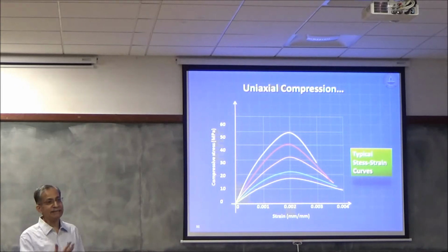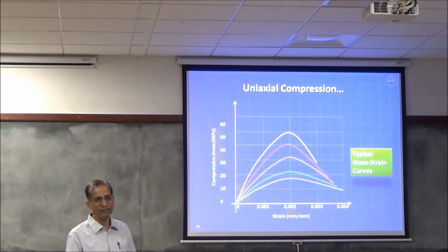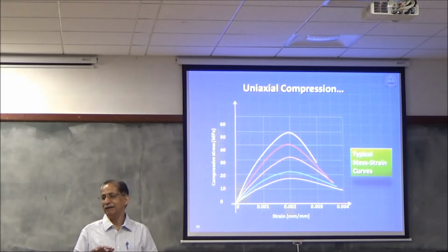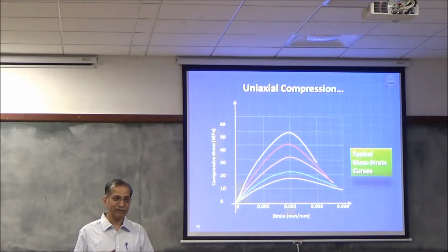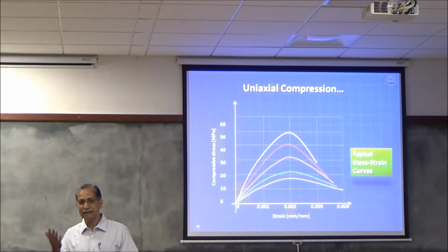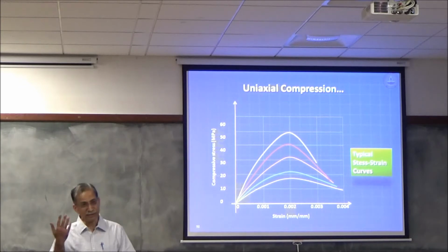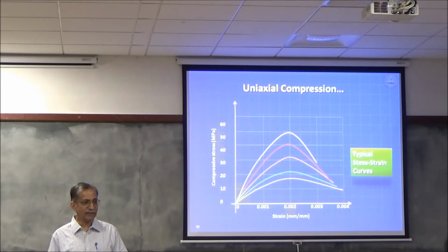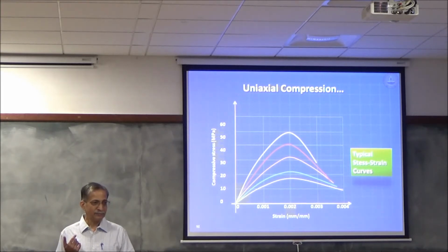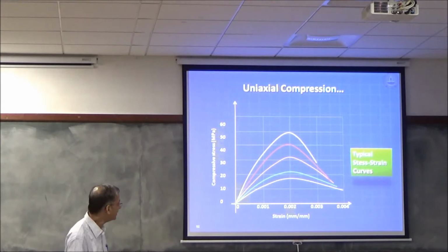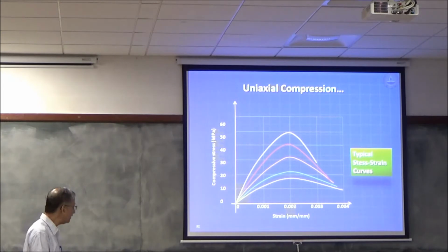And so the density is also slightly more, obviously, but not too much. The variations in density are not so significant as the variations in elastic modulus. Okay. So as strength increases, everything increases. Tensile strength also increases, density also increases, bond strength also increases, shear strength also increases, elastic modulus also increases. Good. So those are the three observations that you have.